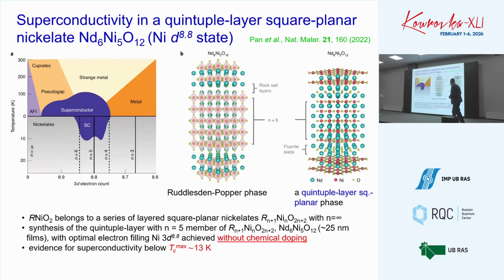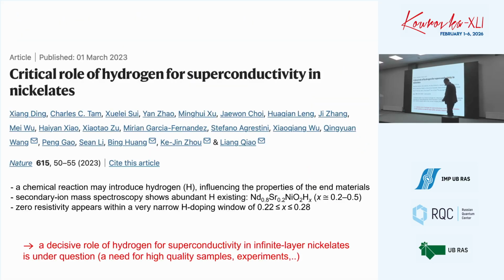And there was even a somewhat funny story about this: in principle we need to dope this system to make it superconducting, but there are many possibilities for how to do this. One of those possibilities is to grow a material, some kind of Nd6Ni5O12, which would by construction have the optimally doped nickel state. And people managed to synthesize this material, and indeed it showed superconductivity with a Tc of about 13 K, somewhat consistent with all the previous series of infinite layer nickelates: yes, indeed, we need to dope the system somehow to achieve some kind of optimal doping, which is related to a maximum of superconductivity in this material.